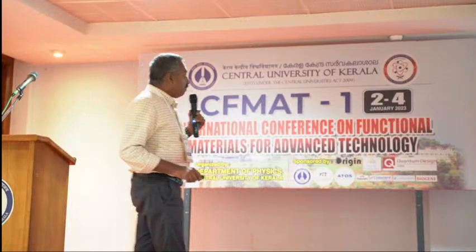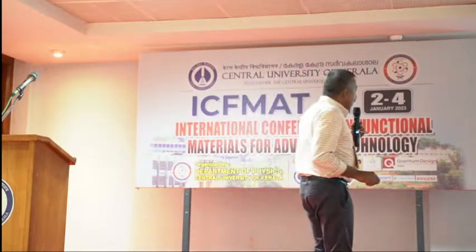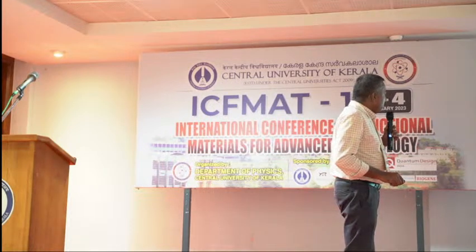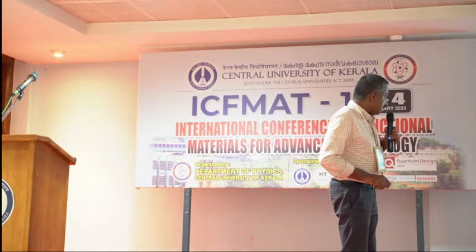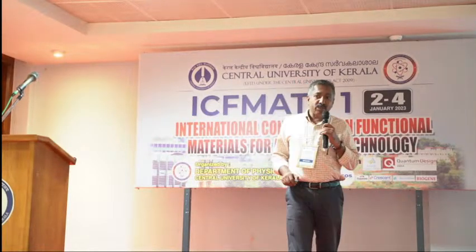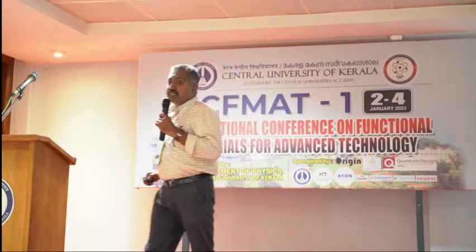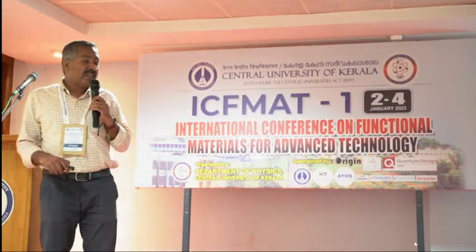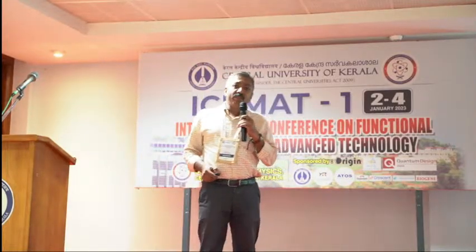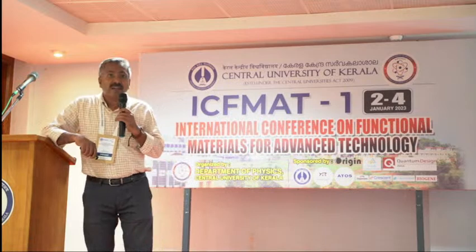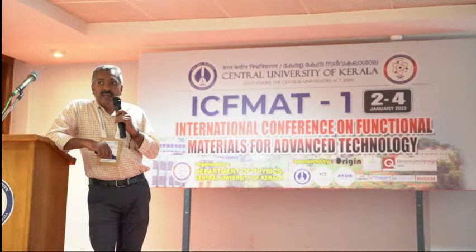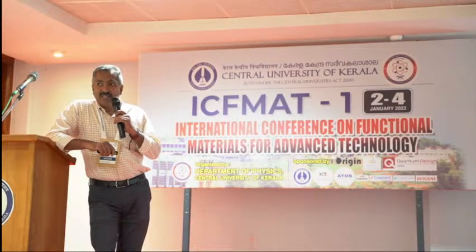And at Au144, this is Au144. And when you go to the plasmonic nanoparticle of 4 nanometer size, you can see that the nonlinear transmission increases for a certain intensity range and then decreases after that. So a lot of people worked in metal nanoparticles and semiconductor quantum dots in those days, and I'm not really going any further into that because of limited time.